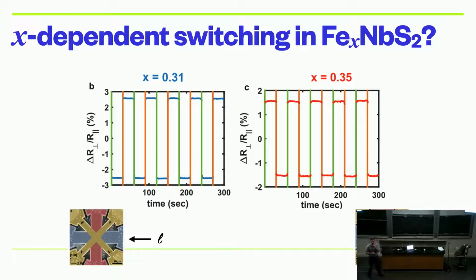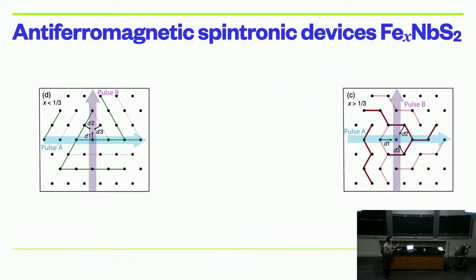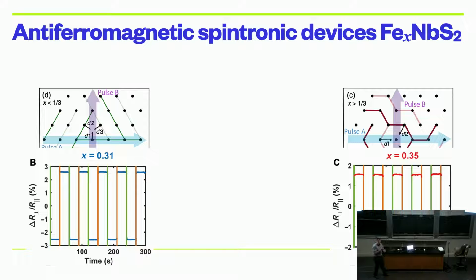But anyway, why was there a difference? We did some neutron scattering, which is a way of figuring out what the magnetic structure is in the system. And it turns out you get 2 different magnetic orders with just that small percent change in the iron intercalation. You get stripy order in the low intercalation ones, and you get this zigzag kind of order in the other ones. And they have opposite anisotropies. They have opposite resistance responses. And so now it all made sense. This is why we were seeing the opposite response: these 2 things had different kinds of magnetic order with exactly perpendicular anisotropies.